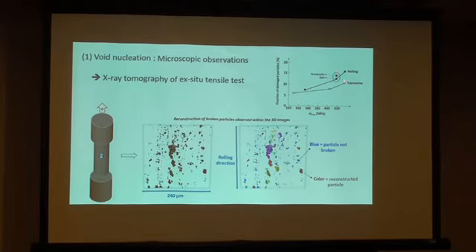So for one of those samples, we extracted a tomography sample, and what you get after thresholding and so on is a binary image made of the broken particles and the matrix here in white. We did a very simple reconstruction algorithm based on simple criteria, which I'm not going into detail about now, but at the end we can reconstruct what used to be a particle before it broke. So you see, for example, here in blue, this is the unbroken particle, and in color, it is a reconstructed particle. Sometimes a very big particle broke into multiple fragments, and sometimes just into two pieces.